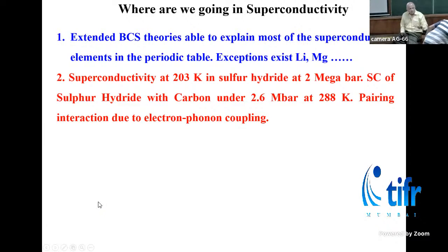So see, the point is that the idea of this hydride came from a theory paper. Ashcroft predicted long back that if you take hydrogen and squeeze it, it will become metallic. And at some point, the hydrogen is supposed to become a superconductor. And it has a high transition temperature because the Debye temperatures are huge, 3000 or so. So these hydrides also have a very high Debye temperature when they form. And that is the reason why when you replace the hydrogen by deuterium, you see that the Tc is shifting towards lower temperature, showing clearly that it is an electron-phonon mechanism, maybe a complicated one at high pressures, that is responsible for superconductivity. So that's why people initially squeezed hydrogen.